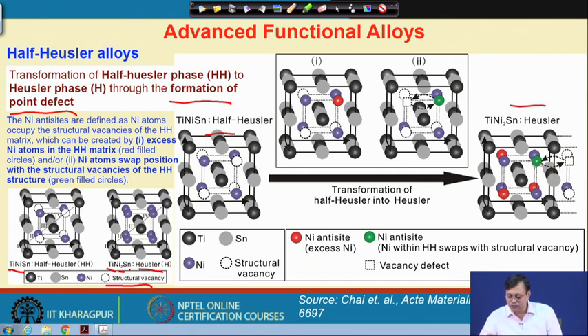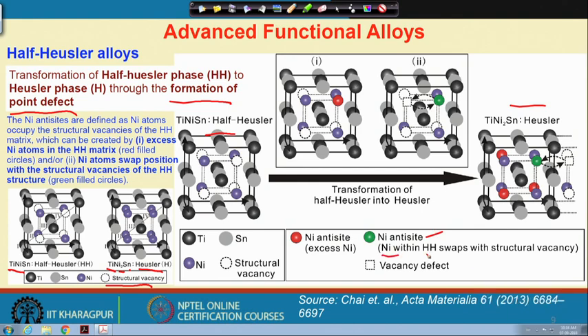To switch from a half Heusler to a Heusler, we need to switch between these nickel sites with the structural vacancy, which basically causes the nickel antisite where we have some excess nickel and so on. So, transformation from a half Heusler to Heusler is also possible. They basically change their positions, and by a vacancy defect we go from a half Heusler HH to a Heusler phase.